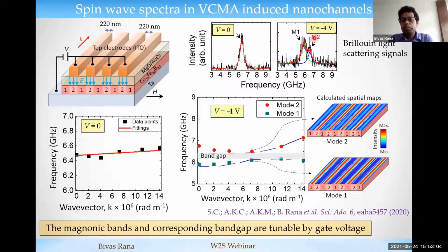But when we applied -4 volt gate voltage, interestingly, this single mode is split into two spin wave modes. If we see the dispersion relation for 0 voltage, it is like the previous blanket film, only a single spin wave mode. And when we applied -4 volt, you can see this mode is split into two spin wave modes, mode 1 and mode 2, and they are separated by a band gap.